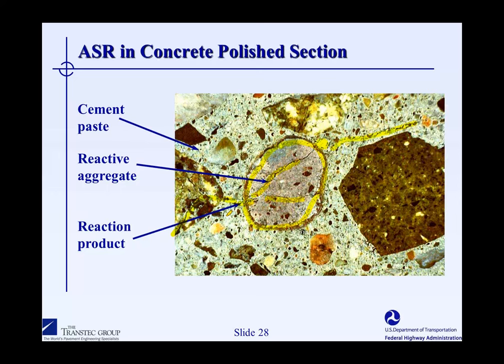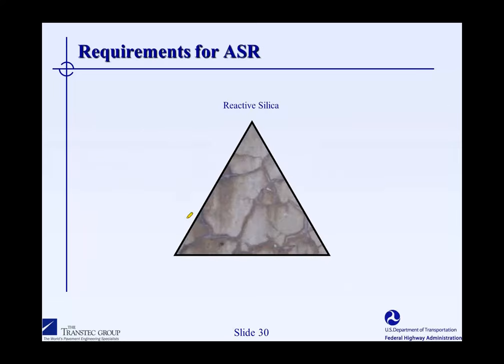If you see something like this, you can see that you've got alkali silica reaction, and not only that, you can see that alkali silica reaction has caused distress in the surrounding cement paste. So you can positively diagnose ASR, at least as a partial cause of any distress that you have in your structure.